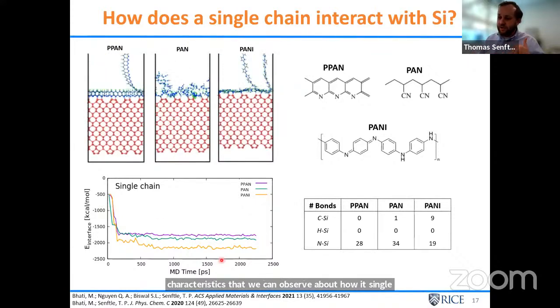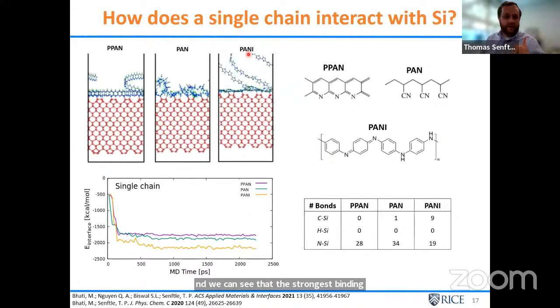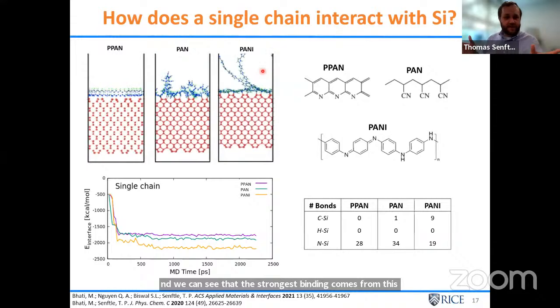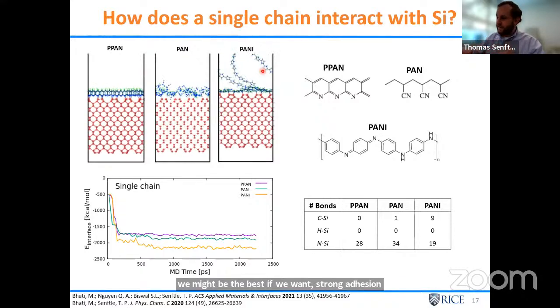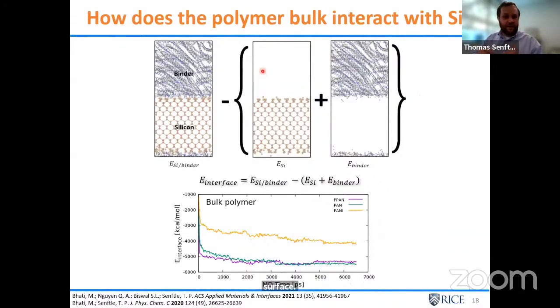And we can see that the strongest binding comes from this polyaniline. Okay, so that would suggest that polyaniline might be the best if we want strong adhesion between the polymer and the silicon surface. So the next thing we did is, let's look at the way that an actual bulk binder interacts with the silicon surface.